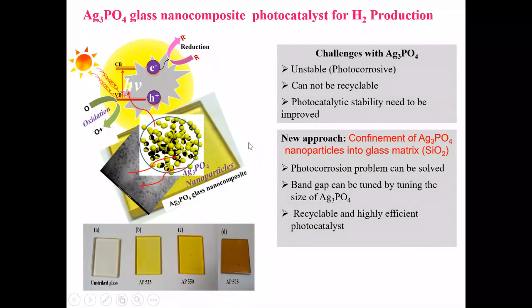Recently, we developed silver phosphate nanoparticles in the glasses, and it is a replacement for cadmium sulfide. You can see the growth of Ag3PO4 in the glasses. This is a transmission electron microscope image. You can clearly see all kinds of nanoparticles inside the glass. If you cut the glass, everywhere you will find the same uniformity. So that is the beauty of this glass, and we use it for hydrogen production.